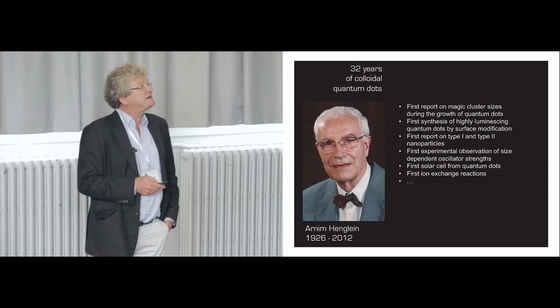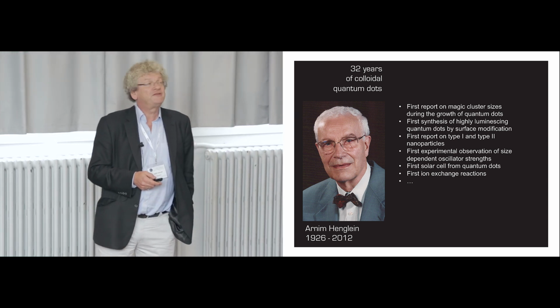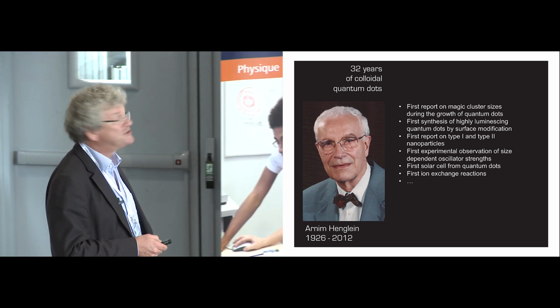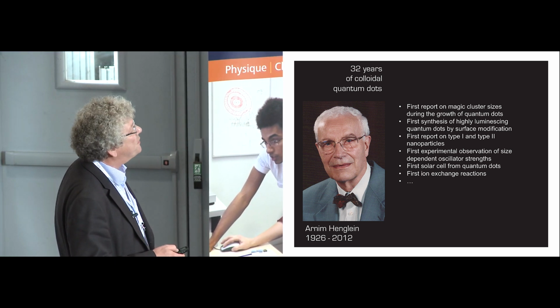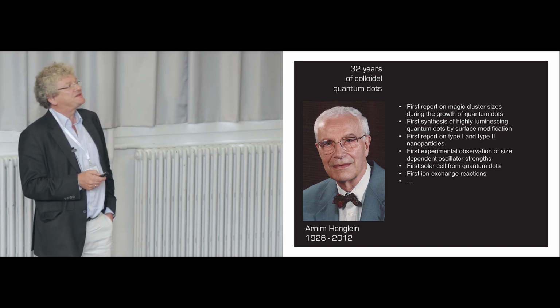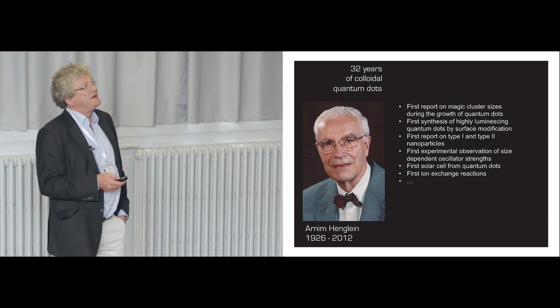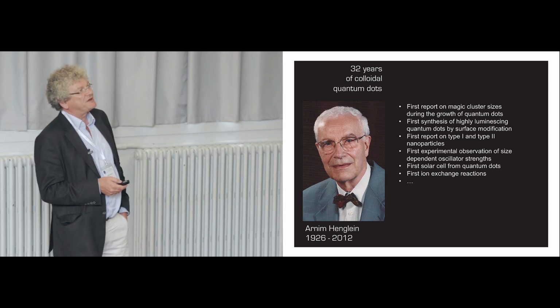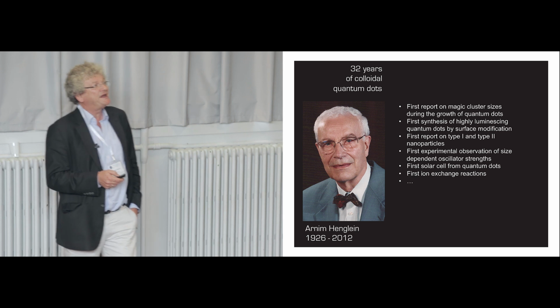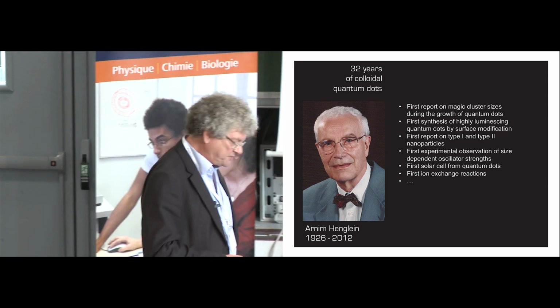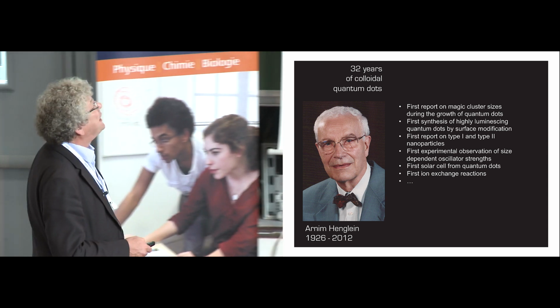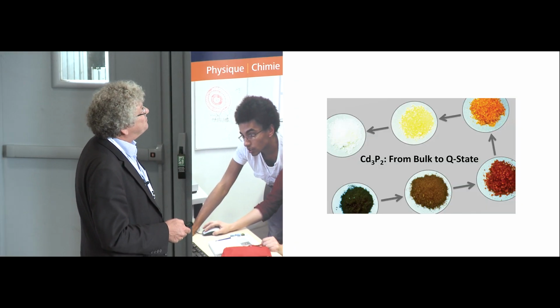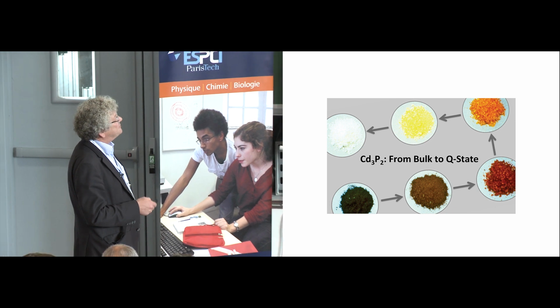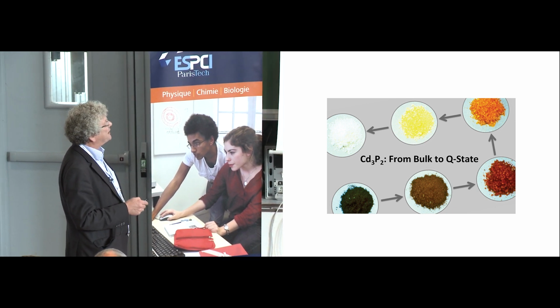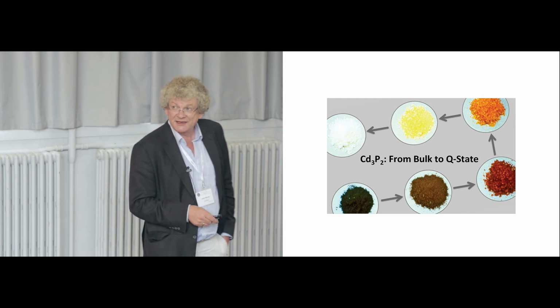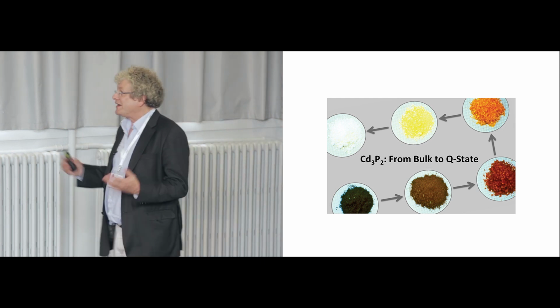During that time, we had many different things we could observe for the first time. So these magic cluster sizes during growth, or highly luminescing quantum dots by surface modification, these type 1 and type 2 nanoparticles, size-dependent oscillator strengths, solar cells, so the first solar cell at that time, ion exchange reactions, and things like this were already pioneered during that time. And this is one of these famous pictures, here cadmium phosphide from that time when I was in Henglein's group, here from black to white, actually making these things. So we knew already quite a lot.